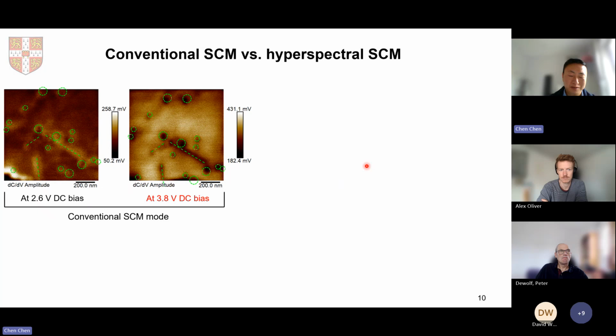And indeed, we did a scan. Here, in conventional SCM mode, we can see at the lower DC bias of 2.6 volts, the fissures show bright contrast. Then when the DC bias increases to 3.8 volts, there's contrast inversion, so the fissures show opposite dark contrast.